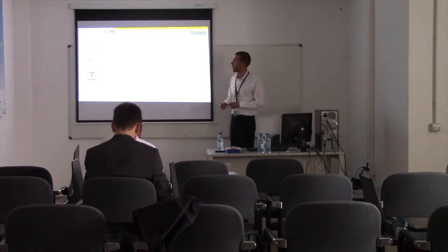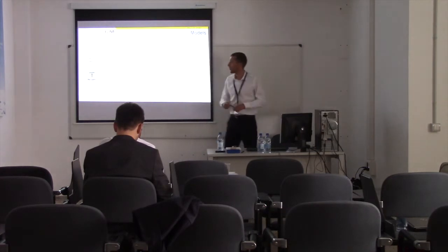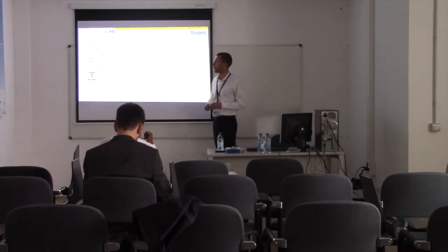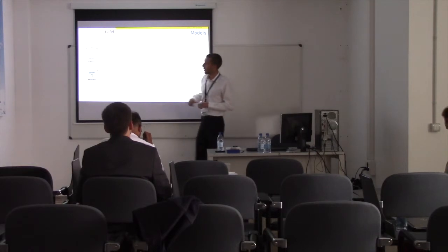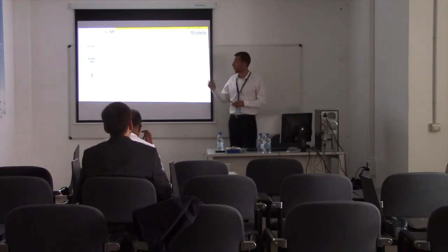For the model, we try to be as near as possible to the machine. So we have a build platform of 100 by 50 millimeters square. It could be bigger, but it didn't seem to be interesting to do such volume. We integrated randomly a powder layer volume, which was 20% larger than the build platform volume. And then we have a recoater system that can spread this powder to create this powder bed layer.